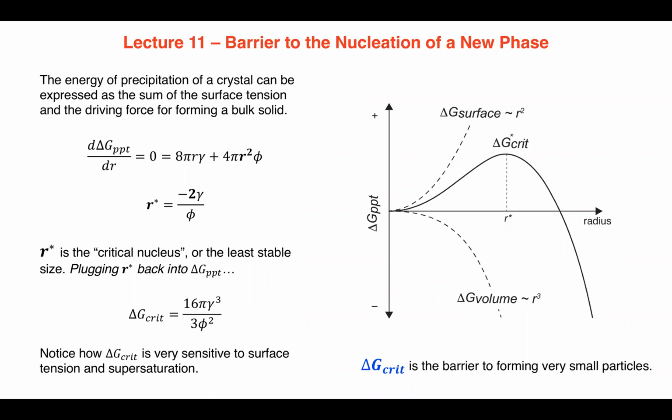Now, let me just say one thing about this. This barrier here is not like a traditional barrier that you're used to thinking about in a chemical reaction. It's actually a thermodynamic barrier as opposed to a kinetic one. So the system's got to traverse all these different sizes, and it has to get over this size that's very unstable. But that's not like a transition structure. It's not like a transition state. It's a ground state energy of one of the particles on the trajectory. That's very different, okay? And as a chemist, I didn't think about that when I first saw this.